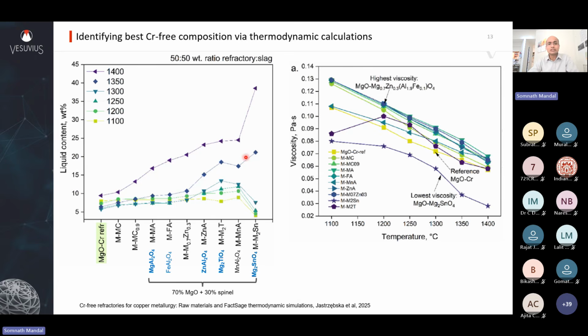So one of the first things we did was thermodynamic calculations using the FactSage software. We used magnesia-chrome refractories, and with that, a 70-30 mixture of magnesia with 30% of each of these spinels: MgAl2O4, hercynite, magnesium titanate or qandilite, the zinc aluminate or gahnite, and then magnesium orthostannate. So these spinels were compared, and from there we got insights that a few of these phases are promising, and this is theoretical analysis, right? We need experimental validation.